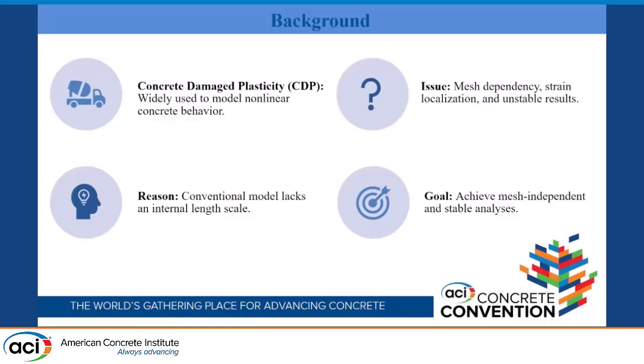Because concrete is a strain softening material, this model suffers, together with the finite element method, from mesh dependency. And mesh dependency will manifest itself in different ways. You may suffer convergence problems in your equilibrium analyses. You may suffer bifurcations in your solution, or misestimate the load redistribution when some part of your concrete structure fails. This is because the basic concrete damage plasticity model lacks an internal length scale. When we test a concrete member in the lab or observe its behavior in real life under an earthquake loading, for example, it behaves at a certain scale. That scale is the centimeter scale, perhaps the meter scale. And as far as the concrete damage plasticity model is concerned, it has an infinitesimal scale, and those do not necessarily match.